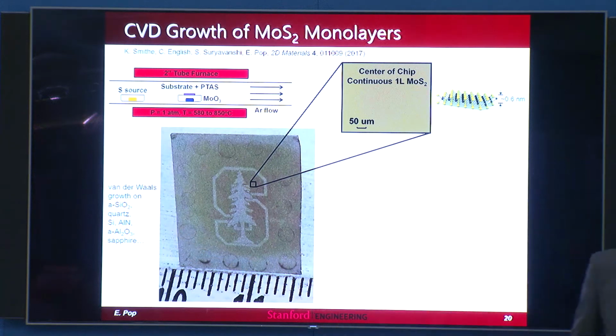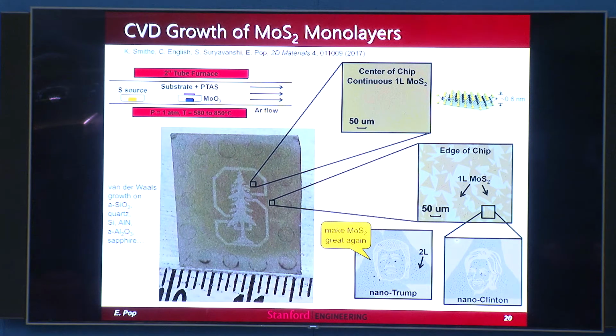This growth can be replicated on pretty much any substrate that we can stick in the furnace, and it's pretty flat. Silicon oxide, quartz, silicon, aluminum nitride, we've grown on sapphire. Anything that you can stick in the furnace that's flat, it'll grow on, and that's actually pretty good for this kind of van der Waals growth. If you look in the middle of the chip, it looks boring, right? It's boring, good boring. It's basically just a flat monolayer, and that's great. If you look towards the edges of the chip, I'll be honest with you, we actually don't get perfect coverage of the chip. And so you get these sort of 100-micron polycrystalline grains, which are not always touching, right? We can go and do a device on one of these grains, but obviously we prefer to work with the continuous regions in the middle of the chip.